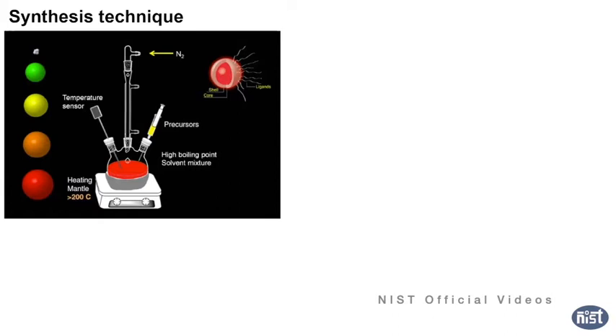You can add the precursor, you can add the solvent, you can add whatever you like. For example, if you need to grow a rod, you need to protect the other two sides of the nanocrystal so it can grow in one dimension. At that time you can add the solution and it can grow. So you can have almost all particles in the same size or same length, so it can give homogeneous particles. I will show you some TEM images, transmission electron microscopy images, later, how beautiful it is.